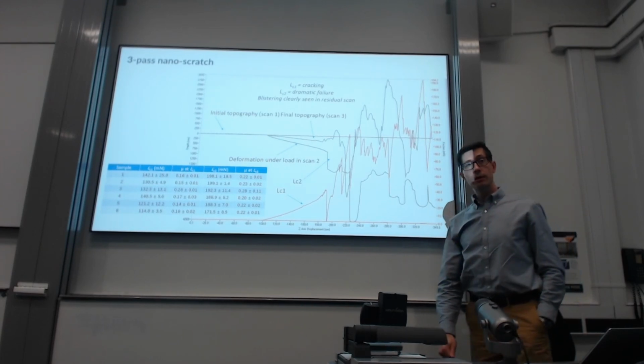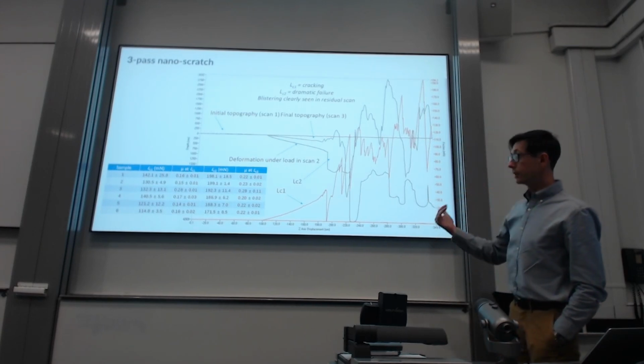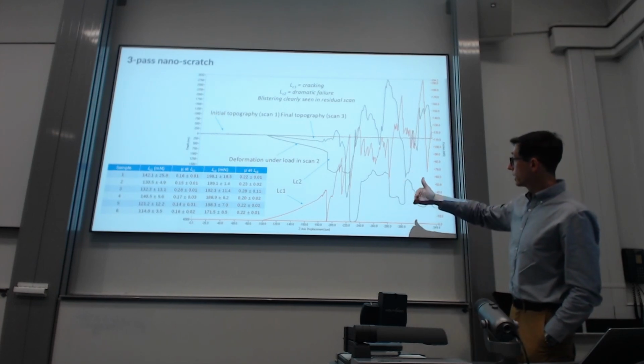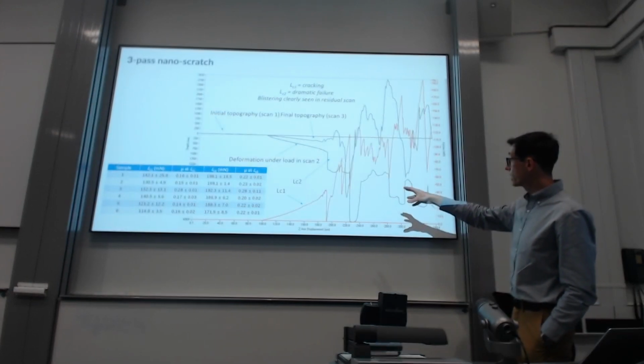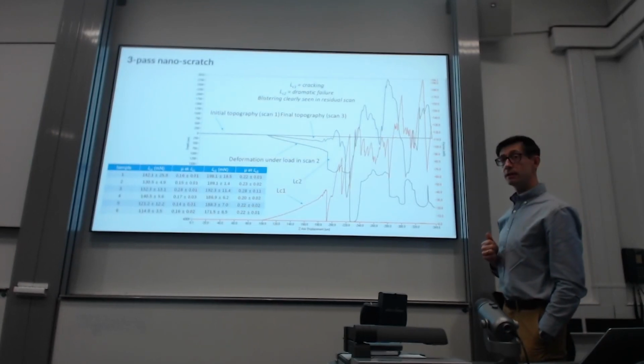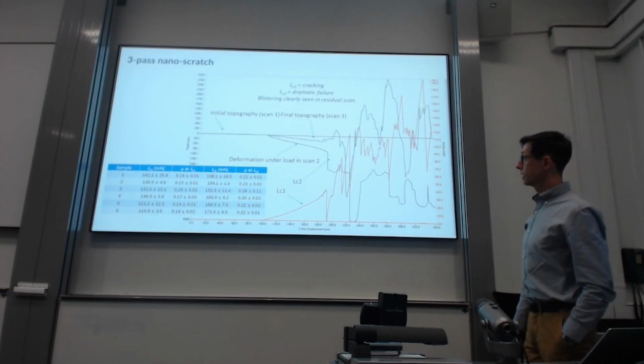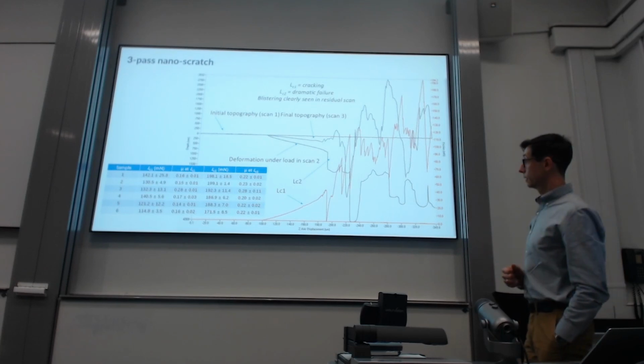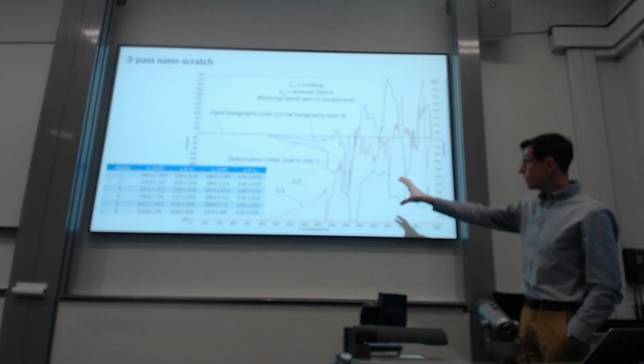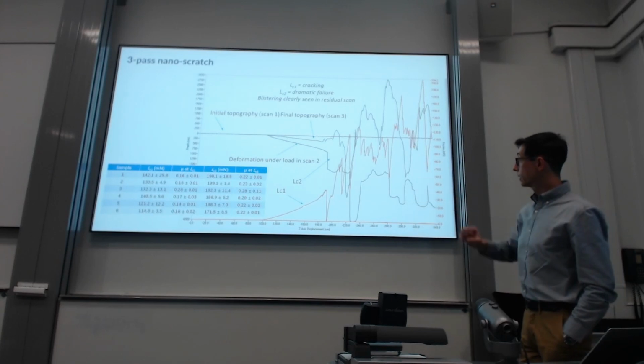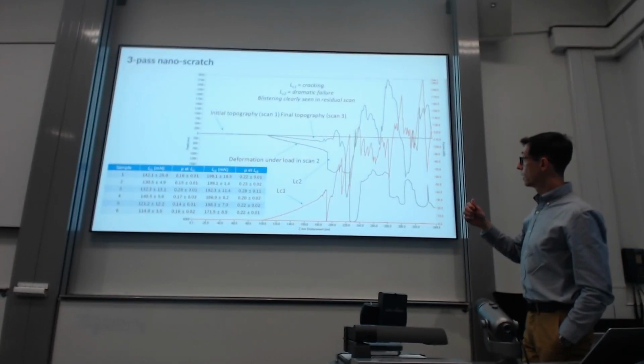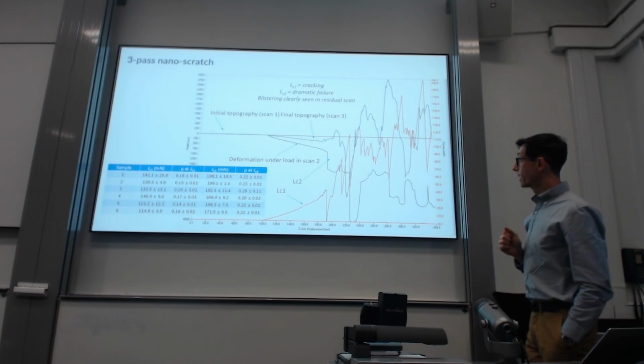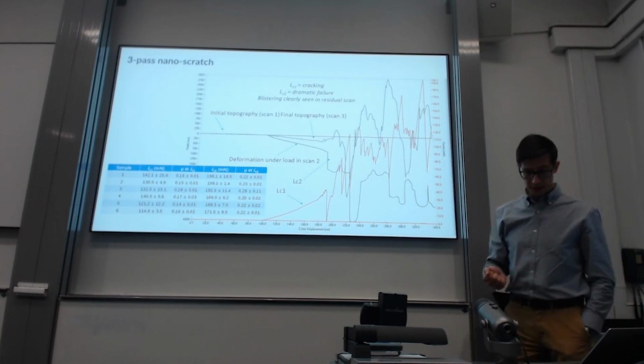So then you can start looking at those curves and analyzing them, looking at the critical events, typically LC1, some sort of first cracking happening, and then some more dramatic failures, and you can quantify them for each of the samples, and also you can look at the friction value at that point. Not much in terms of numbers for that particular set of samples, but overall very helpful analysis in terms of getting into the mechanical response of coating surfaces under this type of loading.